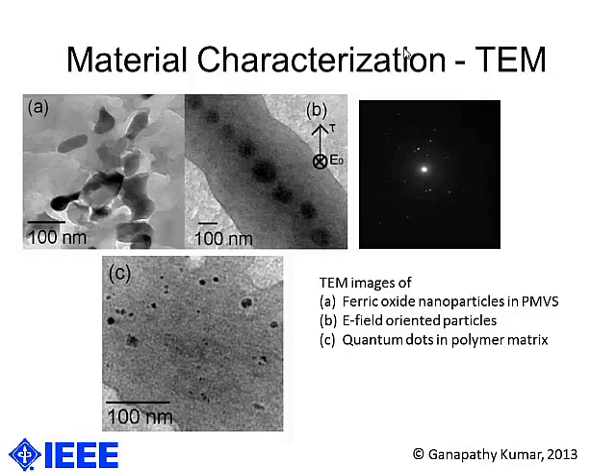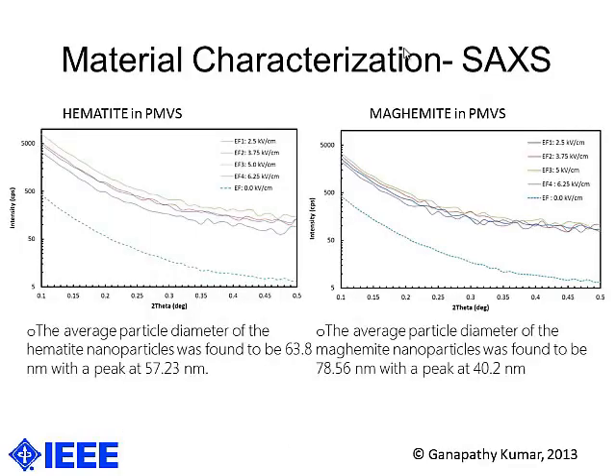And figure C shows that the nanoparticles that we've used in certain cases have dissociated into quantum dots in the polymer matrix itself. Now, for the small angle X-ray scattering, we focused on 2 theta angles between 0.1 and 0.5 degrees because of the large sizes of the nanoparticles that we used in the study. Anything beyond 0.5 degrees was basically noise.